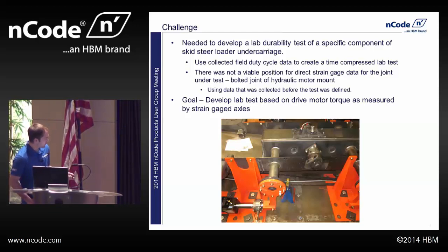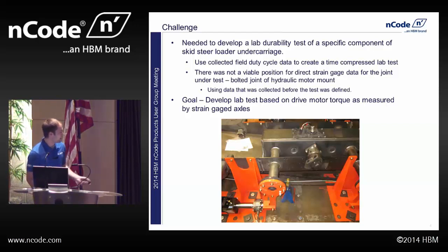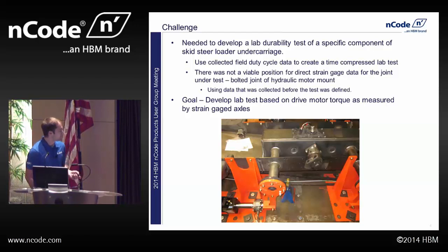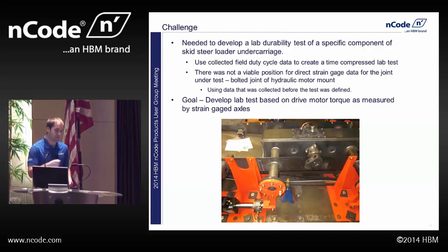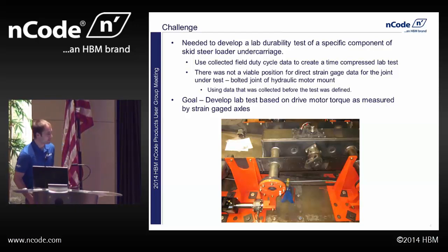This is actually the fatigue test setup. We had the skid steer transmission bolted to the hub, with just a lever arm connected to a servo-driven actuator — you can see the load cell and built-in LVDT there. We had one of these actuators connected to each axle, and the drive motor was actually locked. We filled it full of weld to prevent it from rotating so that all of our loads were reactive right at the drive motor.